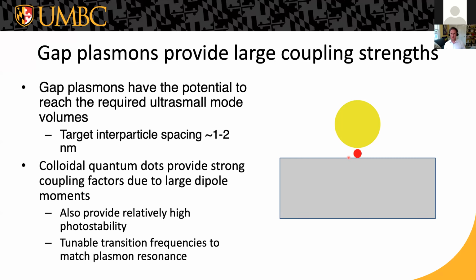And here I'm talking about colloidal quantum dots, semiconductor nanocrystals, particularly cadmium selenide, zinc sulfide, core shell nanocrystals. They're a few nanometers in diameter, which limits the spacing, but what you get in return is a stronger dipole moment, a transition dipole moment inside the quantum dot compared to a single molecule. You get relatively high photostability, so they're less subject to photo bleaching or photo damage from these very tightly confined fields. The molecules are. And also we can just tune the transition frequency in these quantum dots by changing their diameter to match the resonance frequency of this gap plasmon, so that we can get the detuning down to zero and the strongest coupling possible between the two of them.